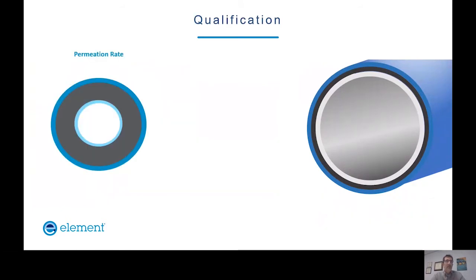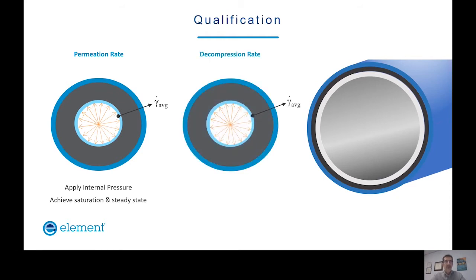As we look further at this pipe, coming back to the cross section, we have things that are called permeation of these polymers. Now, this is a naturally occurring phenomenon, much like helium coming from a kid's balloon at a birthday party. That balloon just won't stay inflated forever. So permeation occurs because it's a polymer. As we apply internal pressure to the inside of the pipe, we see a saturation achieved as these molecules move through the wall of the pipe to get what we call an average permeation rate through the wall of the product. This establishes not just the permeation rate, but then what occurs when we decompress the product. In other words, what happens when we remove that internal pressure.